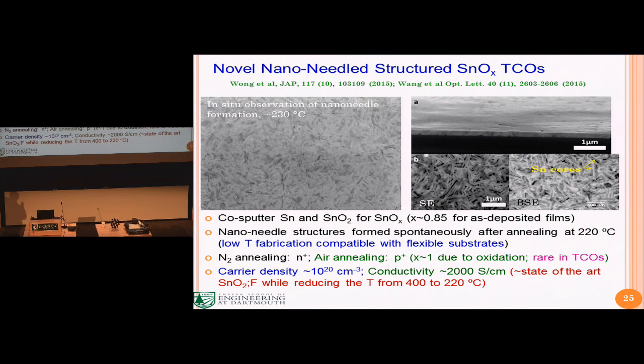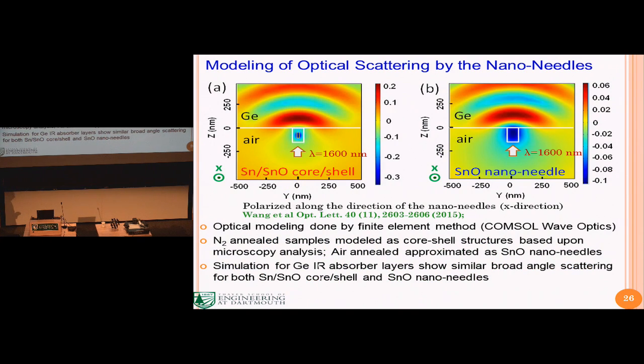So you can see the nanoneedle formation in this case very clearly. Then we start to do some simulations to see how well this structure scatters light. Indeed, if you do the finite element Maxwell equation, you can see it does scatter light in a pretty broad angle. This is the case with the tin core, this is without. Basically, the scattering patterns look very similar, but if you calculate it quantitatively, the scattering efficiency with tin core is slightly higher, but it also comes with some loss in the visible regime.